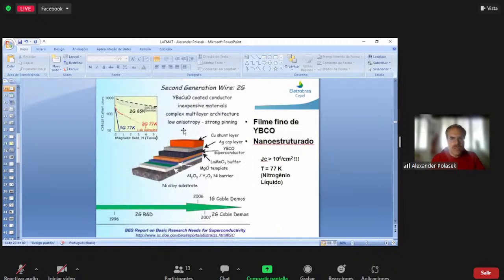And here's the architecture of a typical second generation YBCO tape. It's very different from the others, as I told you. I showed you that most superconducting wires have a conventional metallic matrix with filaments of superconductor. However, in the case of YBCO, you have a multi-layer architecture. It's analogous, similar to semiconductor compounds.